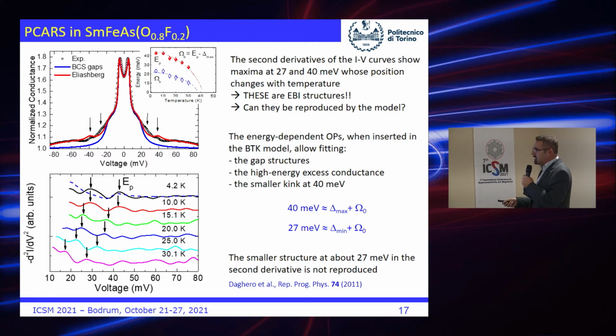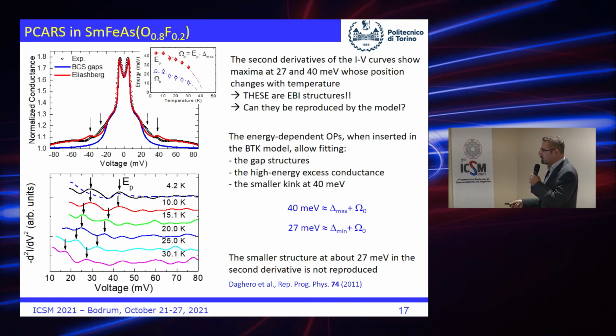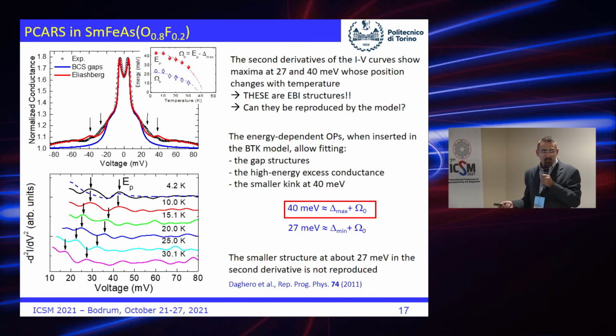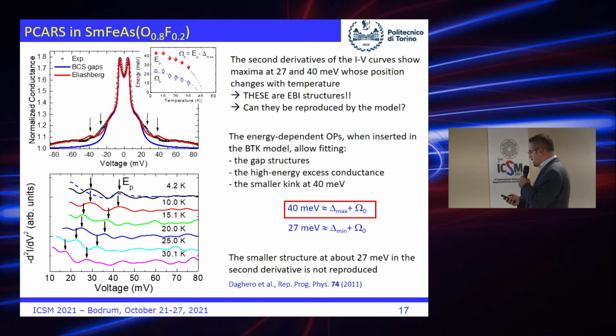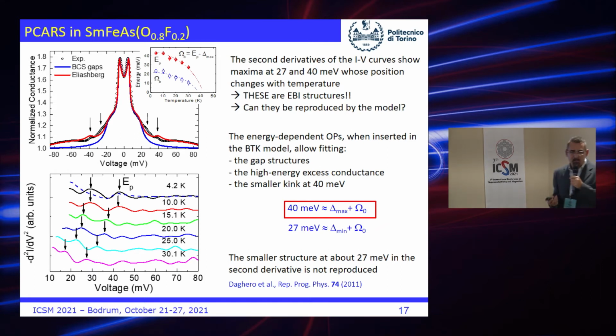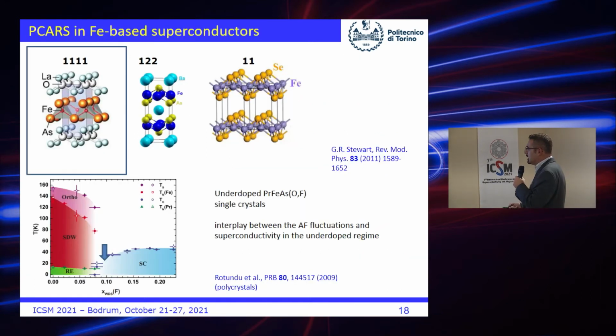if you take the derivative of this red curve, you obtain this dashed line here that reproduces the peaks at about 40 millielectron volt. Note that 40 millielectron volt is nothing but the maximum value of delta, which is about 20 in this case, plus the position of the boson, which is 20. Okay. So we don't know why we do not resolve this smaller peak, but this is still unknown. Probably it is due to the fact that the real shape of the spectrum is not simply Lorentzian; it is something slightly different.